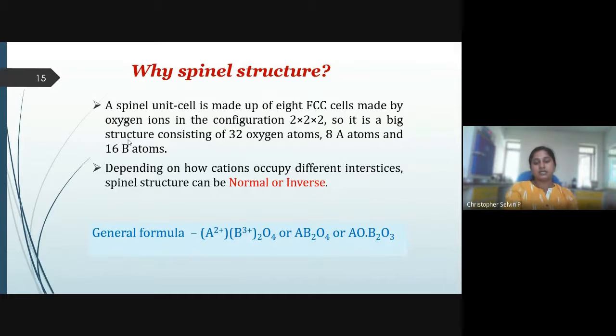A spinel structure has a unit cell which is made up of 8 FCC cells made by oxygen ions in an octahedral configuration. So it is a big structure consisting of 32 oxygen atoms, 8 A site atoms, and 16 B site atoms. Depending on how cations occupy different interstitials, the spinel structure can be normal or inverse. The general formula is AB2O4, where the A ion is in 2+ state, whereas the B ion is in 3+ state.